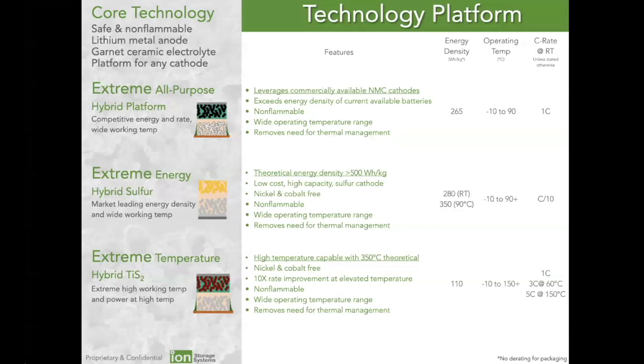I showed you some of the data for lithium sulfur, which again, we've achieved sort of 280 watt hours per kilogram, but we are on track to get towards the 500 watt hours per kilogram. And now these are no nickel, no cobalt, very, very cheap cathode materials. And then again, the possibility of making really high temperature batteries. These can go 350 degrees C or so. So there are a number of unique applications that this would be, again, uniquely capable of addressing. And also the fact that we get so much higher current density available at the higher temperatures.